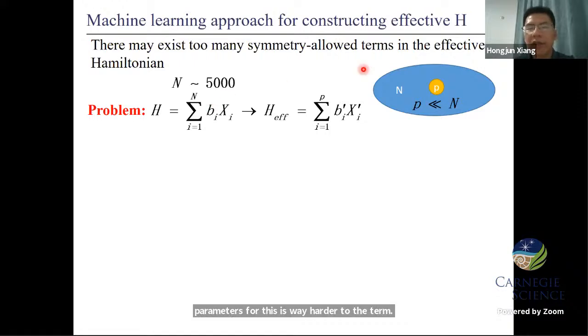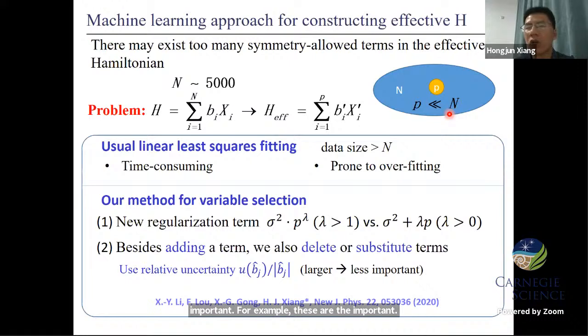But actually, we found that usually to describe a system accurately, not all interactions are important. Maybe only a small portion of interactions are important. For example, the important interactions are much smaller than N. So important interactions might be only on the order of 100. So the problem becomes how to select the important interactions from all these interaction terms.